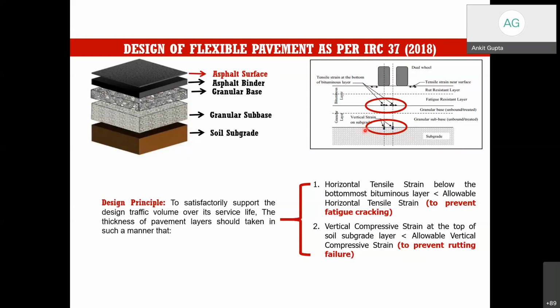and it should be lower than the allowable vertical compressive strain. So this is one basic fundamental. The other fundamental is that for fatigue cracking, at the lowermost layer of the bituminous layer we have to measure the horizontal tensile strain, and it should be lower than the allowable horizontal tensile strain to prevent fatigue cracking. So these are the two basic principles for the design of a pavement as per IRC 37.